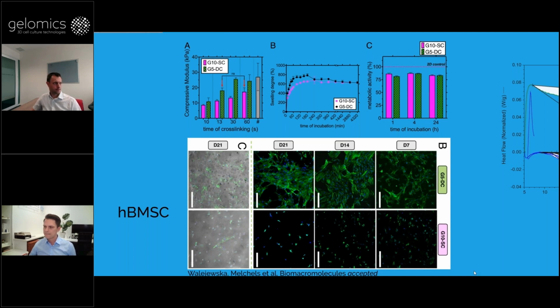I think it is important. It has been shown in the last few years that not looking just at the stiffness but more at the viscoelasticity matters, and it's been shown that in viscoelastic gels you get different behavior of cells than in purely elastic ones. On the other hand, most tissues have about the same viscoelasticity, as in there's like a 90% elastic, 10% viscous component. So it's not like we have a very huge range.